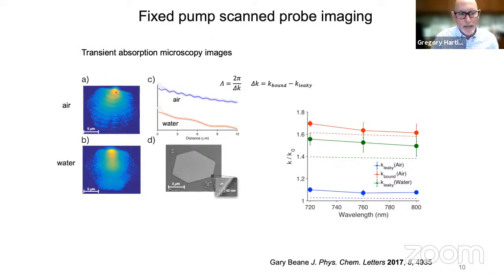What's happening here is, again, when we hit the edge of the plate, we excite propagating plasmon modes. We have two of them: the bound mode at the metal-glass interface and the leaky mode at the metal-air interface. And they have different wave vectors. So as they move away from the excitation region along the plate, they interfere with each other. That interference creates this wave-like structure in the image. So we're looking at the interference between the bound and leaky modes.